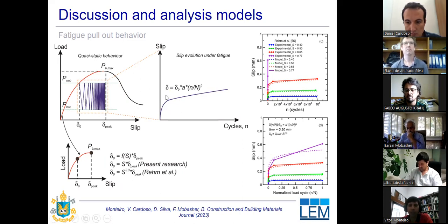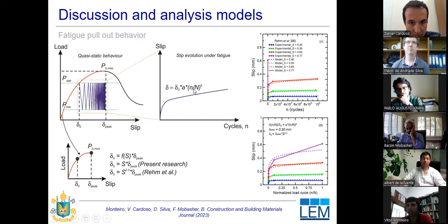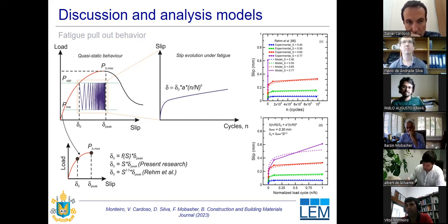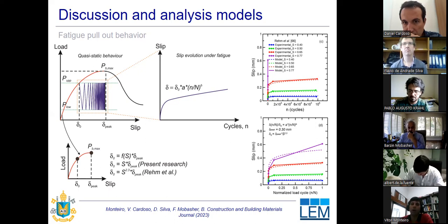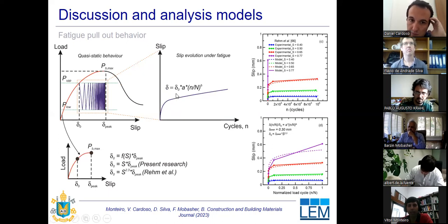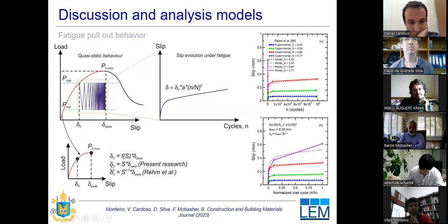And for this research, we propose this power law, which is based on the initial slip, delta zero, and the index number of cycles, which ranges from 0 to 1, where 1 is when there is the rupture of the pullout from the specimen. This model is largely dependent on the initial slip, which can be calculated based on the quasi-static results. So for my experimental campaign, we could verify good fitting with a linear equation for the initial slip, delta zero.